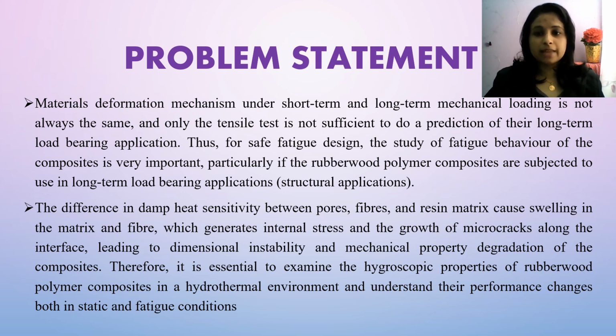For example, the difference in damp heat sensitivity between pores, fibers, and resin matrix causes swelling in the matrix and fiber, which generates internal stress and the growth of microcracks along the interface, leading to dimensional instability and mechanical property degradation of the composites. Therefore, it is essential to examine the hygroscopic properties of rubber-wood polymer composites in a hydrothermal environment and understand their performance changes both in static and fatigue conditions.